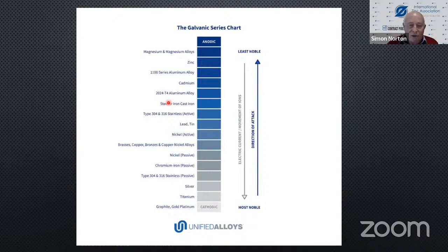Just as an aside to you as engineers, be aware, and in fact, beware. Not only be aware, but beware. If you have active stainless steels and you combine them with materials that sit either down here or up here, you could have a galvanic cell. So it's very important to make sure that when you're using stainless steel, it's in the passive form. In other words, that it's exposed to oxygen, oxygenated water, oxygenated wastewater, or to seawater in particular that's highly oxygenated. But let's move on and get back. Let's just stick to zinc.